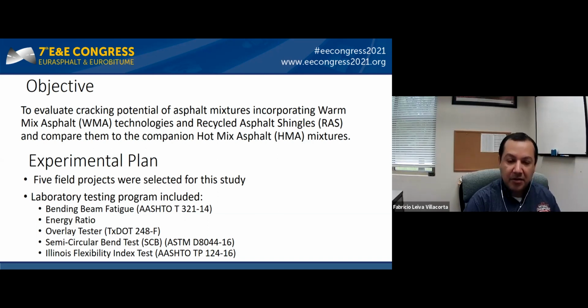The main concern about this study was that asphalt shingles need higher temperatures during mixing to activate the binder that is part of the shingles. If we were to use Warmix technologies that typically tend to lower temperatures during production, that was the main concern, that activation was not actually happening of the binder from those shingles.